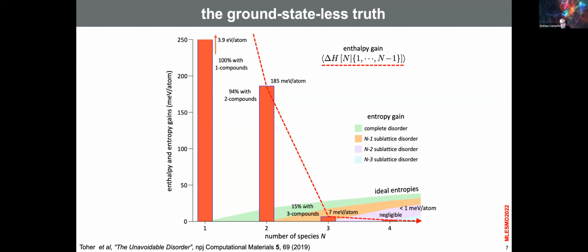But if you go to the ternaries, look at here, only 15% of the ternary compounds have a stable ternary configuration and are not split into a sum of binaries. And the gain is only 7 milli-electron volts per atom, which, compared to room temperature entropy, x log x, is much lower. And then if you look at quaternaries, you have only a 1 milli-electron volt push towards stabilization, which compared with the ideal entropy is negligible. So now you understand why, if you go into the ICSD database, quaternary and pentanary compounds, in the case of metals, are most likely disordered. That's why there are no ordered phases reported for metals with 7, 8, 9, etc. species. Looking for them is really a waste of computer time, and a waste of time.